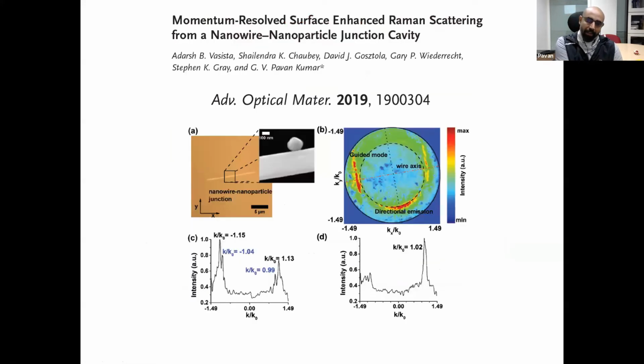Now we also have extrapolated this technique to the nanowire nanoparticle junction, where we see so-called guided modes in this kind of interaction, and this leads to some very interesting characterization of optical fields, all thanks to the surface enhanced Raman scattering. In this particular experiment, what we have shown is that the nanoparticle only carries the molecules, which means that there are no free molecules in the interaction. By exciting the Raman dipole between these two nanowire junctions, you are now exciting the whole plasmon, and this plasmon can be directional in nature. It also gives rise to guided modes, and this can lead to some very interesting questions in the nanowire nanoparticle interaction studies.